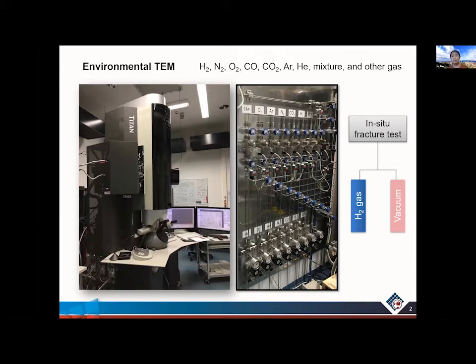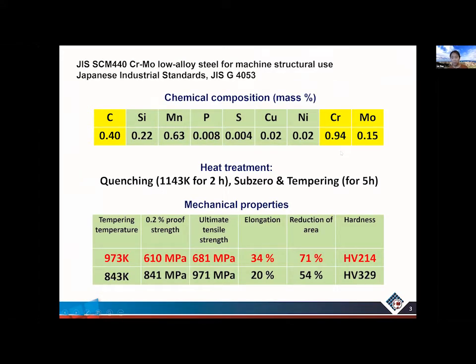And using the TEM, we can do in situ crack tests inside the TEM and observe the deformation process in the microstructure. And we can use either vacuum or the gas environment. So the material is the same as Professor Kubota just mentioned, but we choose a material with a higher tempering temperature, which results in a softer material. You can see the strength and hardness all decrease, and also the elongation, the ductility, increases.